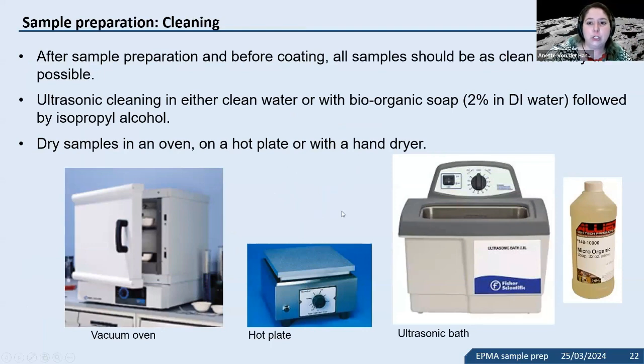When you're finished, there's also something called bioorganic soap that's specifically for abrasives, like if you do EBSD polishing with Syton, that's good to replace it. And then letting the samples dry either for a specific time or speeding it up by having them in a vacuum oven or on a hot plate can also be useful, because again, it helps with the pump down time of when you put the samples in.